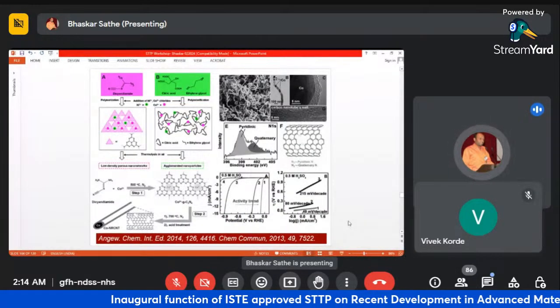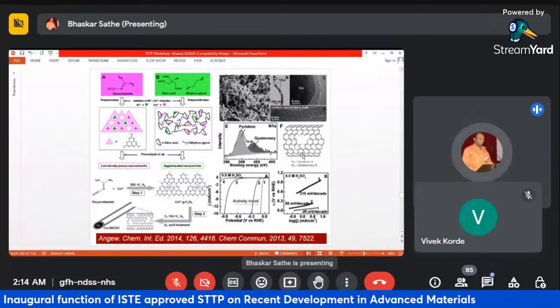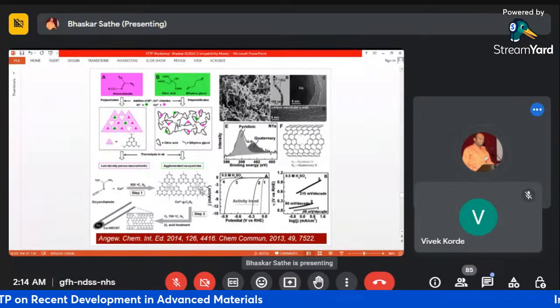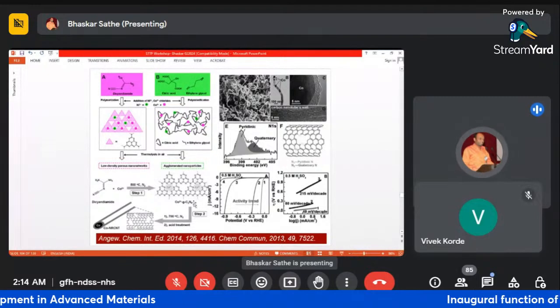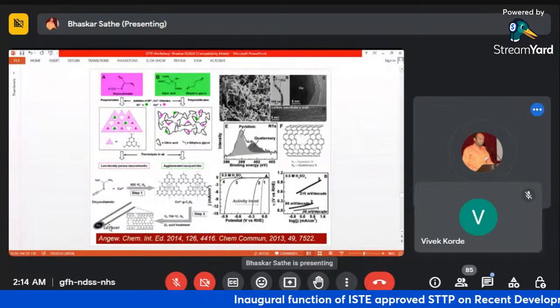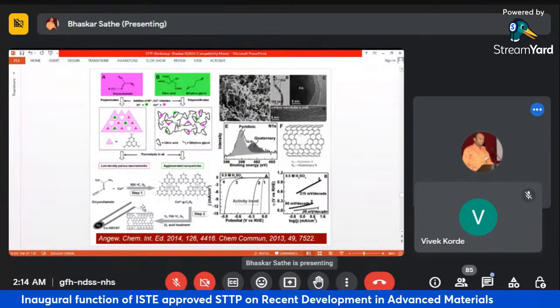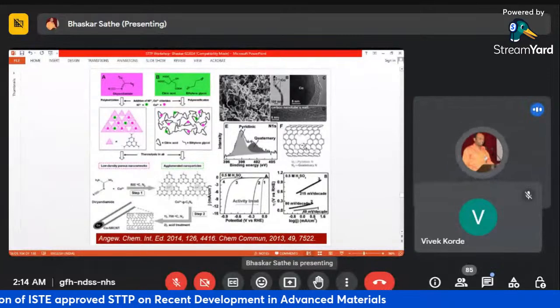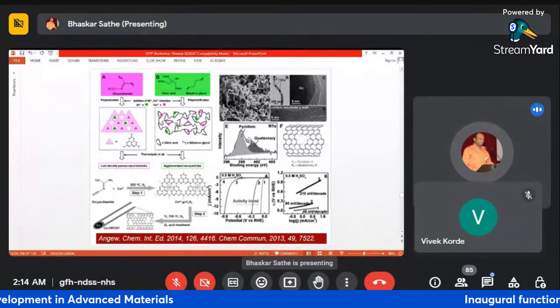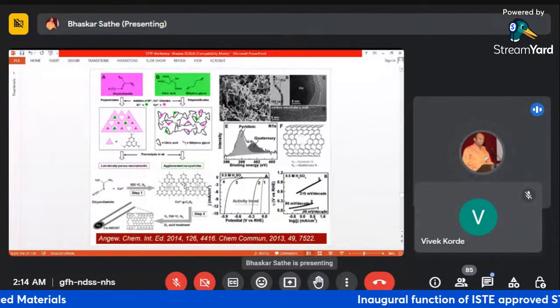Another system where we accidentally made nitrogen doped carbon nanotubes. Our idea was to develop carbon nitride doped with cobalt, which we heated to 700 degrees centigrade. We got cobalt nucleated nitrogen doped carbon nanotubes, and the nitrogens are of two types, pyridinic and quaternary nitrogen. These two nitrogens are more active centers for hydrogen production.